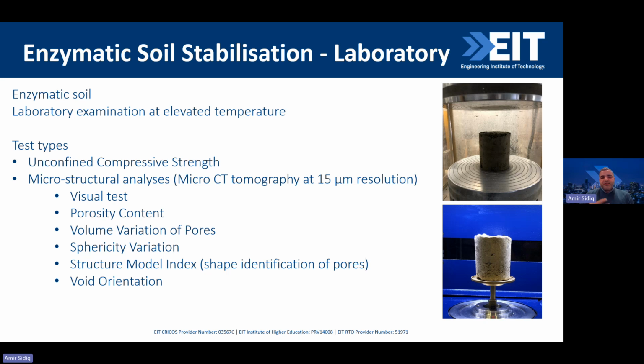So based on the output of these, I actually did some visual tests: the porosity content, the volume variation of the actual pores, what their volume and ranges are, the shape of these pores, and how they change. There are different criteria of the shape, known as the structural model index. And once I knew the structural model index, I went to the orientation, the angle of individual cracks or individual voids within the entire sample.